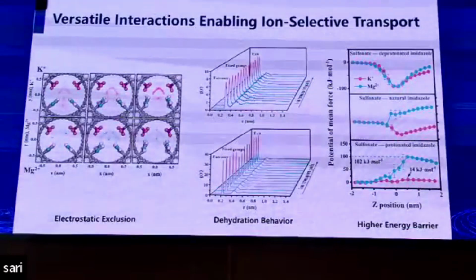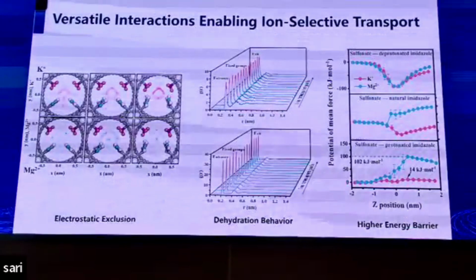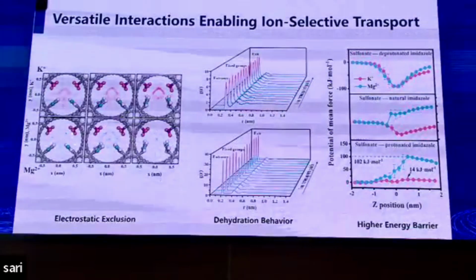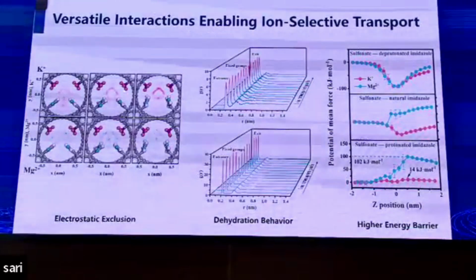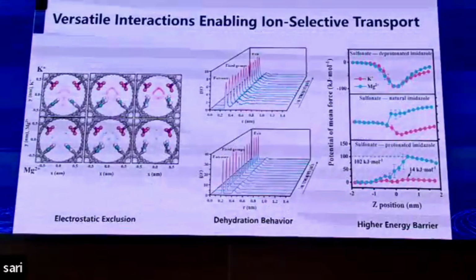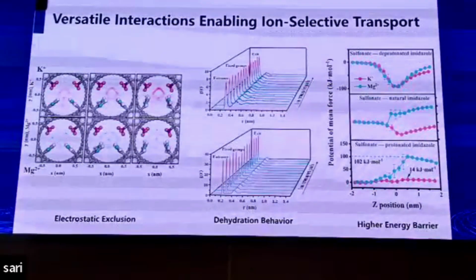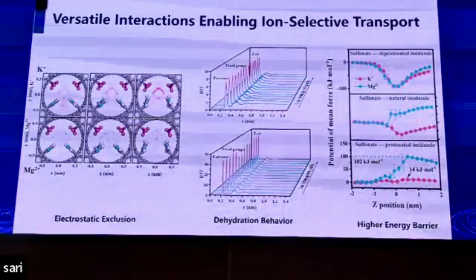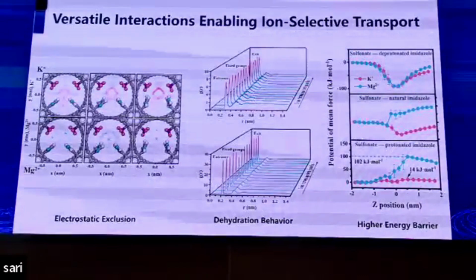With the dehydration assumption, we can look at the two-dimensional distributions. For the monovalent ions, it's still nearly the same when passing through the pore channels. But for the divalent ions, we can see that it decreased a lot, which means their distributions become lower and lower, fewer and fewer.